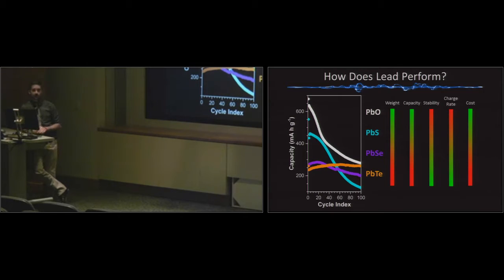So how does lead perform when you actually use it? I made 4 different types of lead, all of the chalcogenide family. And chalcogenides are basically the group of the periodic table starting with oxygen and going through sulfur, selenium, tellurium. I've shown some cycles from that data there on the left, where you have the cycle index, where each cycle is 1 charge and 1 discharge, and then the capacity that you got for that cycle. I show it here for 100 cycles. These colored bars are different properties of the materials, and basically as you go up or down the group from oxide to telluride, the properties trend good or bad.